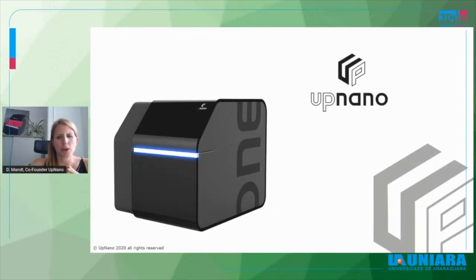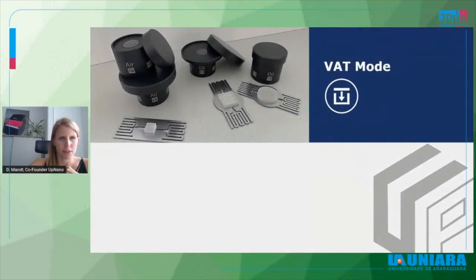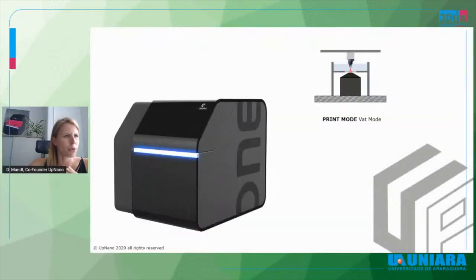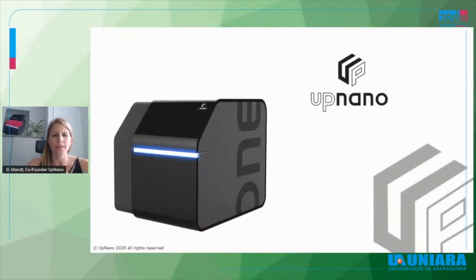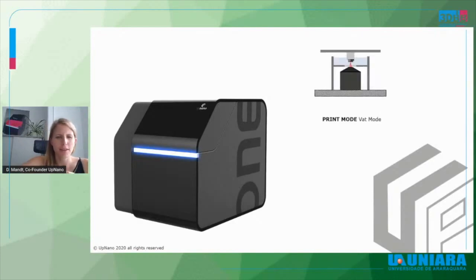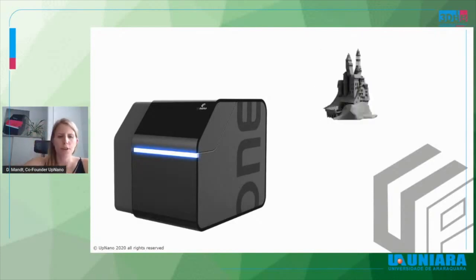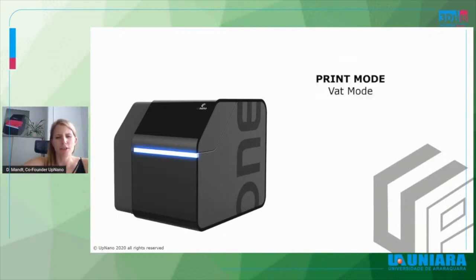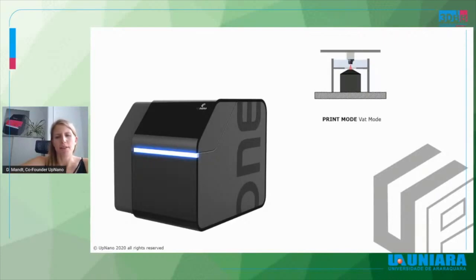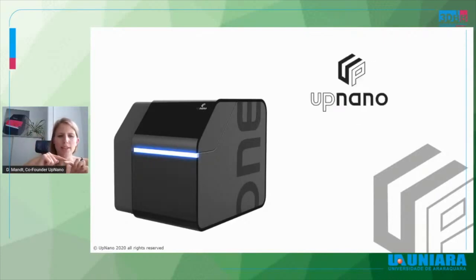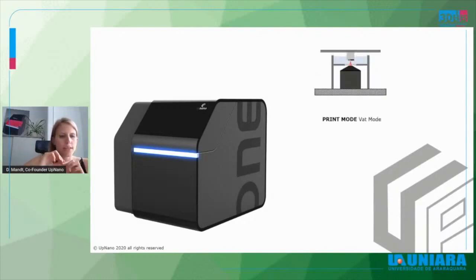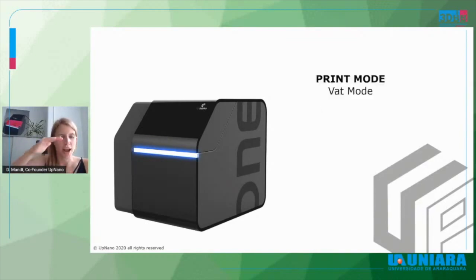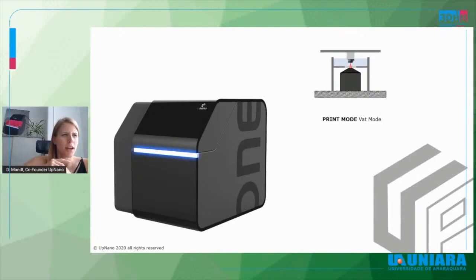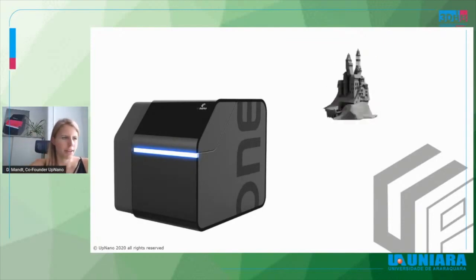Another print process is called the vat mode. Using the vat mode, you can also print higher objects. So in this printing mode, a material reservoir is placed on top of the objective. And then again, the structure is hardened layer by layer. But in comparison to the other mode, here the distance between the laser and the current writing layer always stays the same, and the laser is not focused through the material which is already hardened. Therefore, you can achieve much higher objects. This is possible up to 45 millimeters in height.